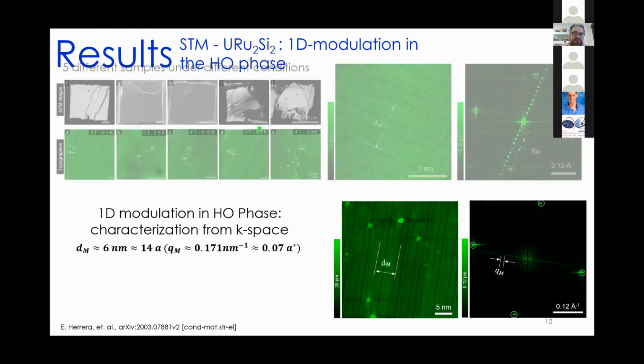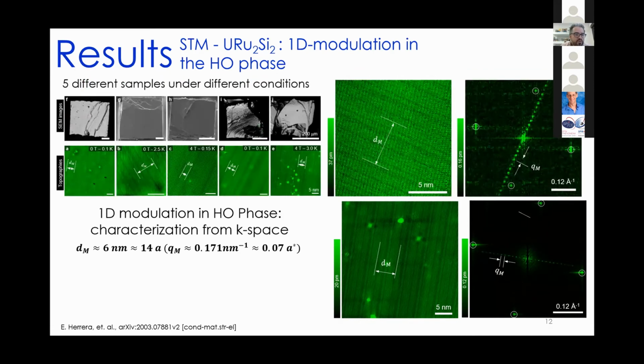So we observe the same one-dimensional pattern on 5 different samples after cleaving at low temperature. Here we have images of all the samples that we have measured, and here we have topography images of each one of them. As you can see here, we also have the same one-dimensional pattern, even under different temperatures and different magnetic fields. So in all the samples, we observe the same 1D modulations with the same periodicity, 6 nanometers.